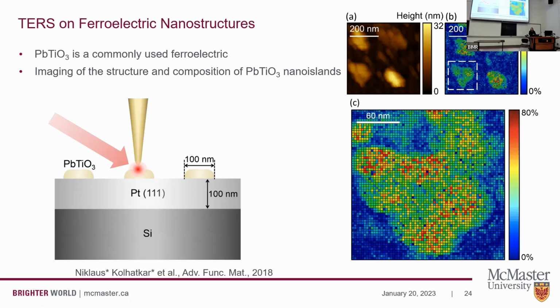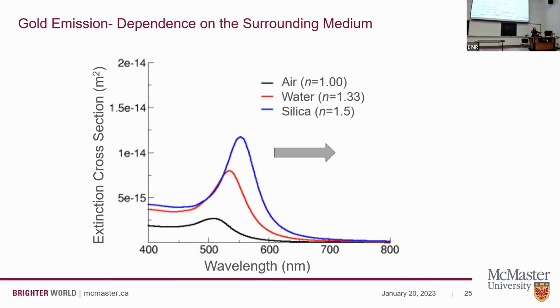We then tried to push the spatial resolution further. So we focused on one of the islands in the white box, and we imaged it. In this image, which corresponds to 60 nanometers, each pixel is about 3 nanometers. So we really clearly see the island. That's great, but it doesn't give us any information regarding the crystal phase of the material.